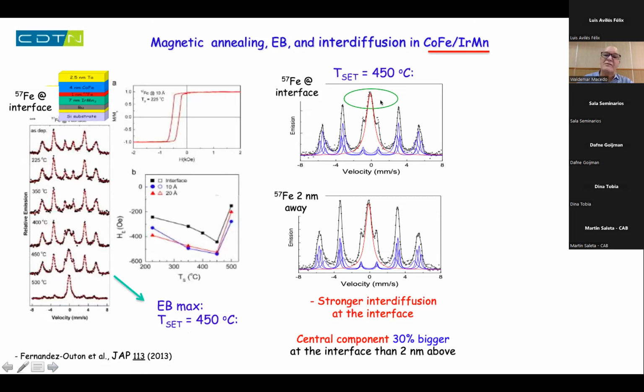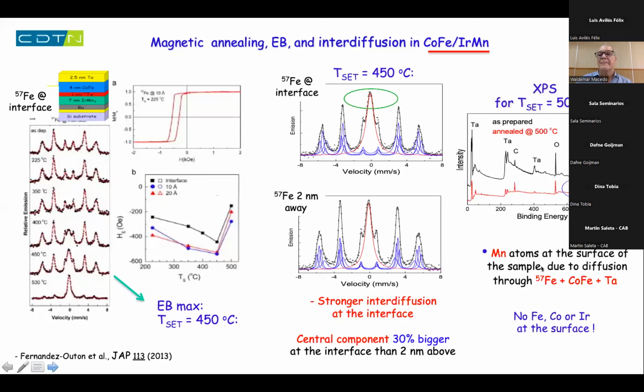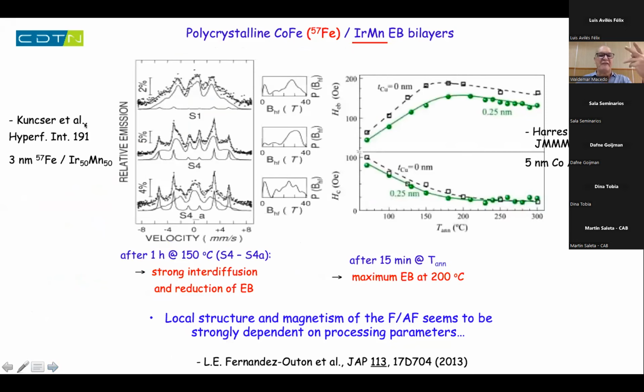You see also, doing XPS, that the manganese diffuses all the way through this stack and appears at the very top surface of the stack. Like you see here, manganese is going through the whole stack. What you can say is that our results are very different from what you get from different groups. And the magnetism and the structure of the interface for this system is very dependent on the processing parameters.